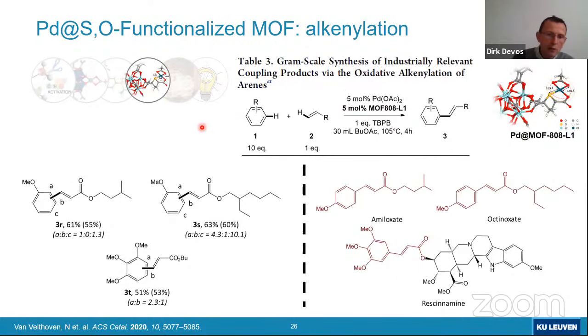We also took that to larger scale. For instance, these are a couple of the molecules which you see here that Niels also made at larger scale, at gram scale, synthesis-wise. And for instance, these two molecules, these are, of course, UV absorbers. So you would find them, amiloxate and octinoxate, in sunscreens. And this molecule, which again has this cinnamate motif, rescinnamine, is actually a drug molecule that you would take if you have hypertension problems, if your blood pressure is too high.